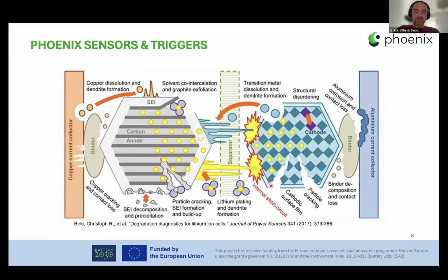So this graph describes the main degradation mechanisms that can occur in a battery chemistry. Starting from the anode side, copper is a widely used current collector. We can see copper dissolution and dendrite formation after the dissolution. Also, the copper can crack, and contact loss between the binder and the current collector can happen.